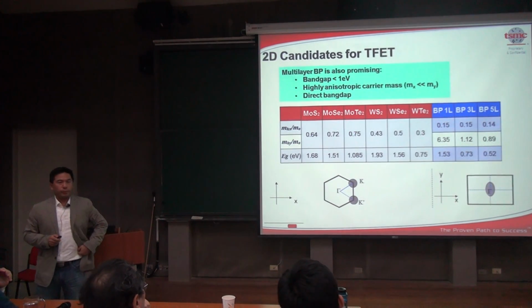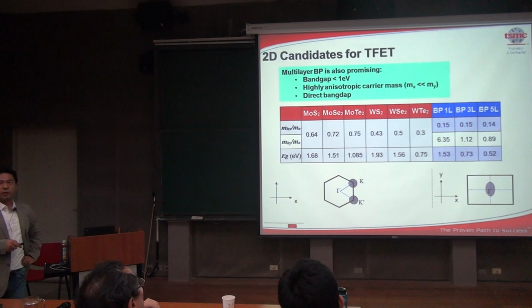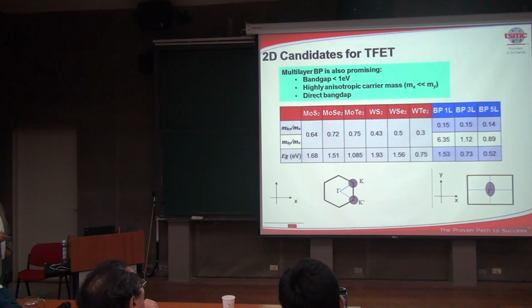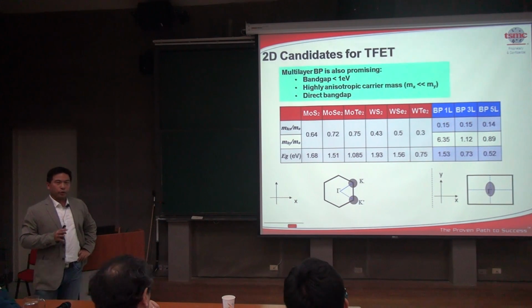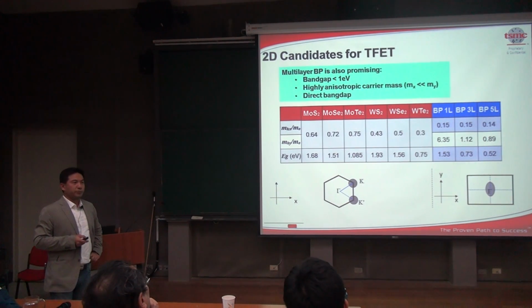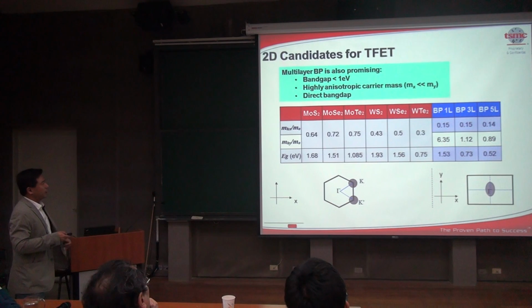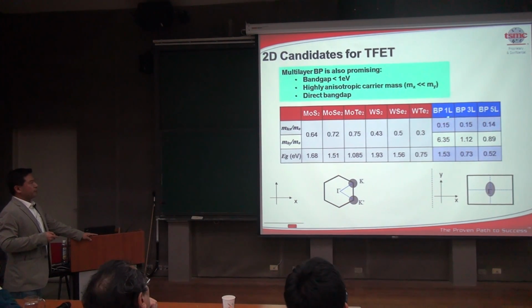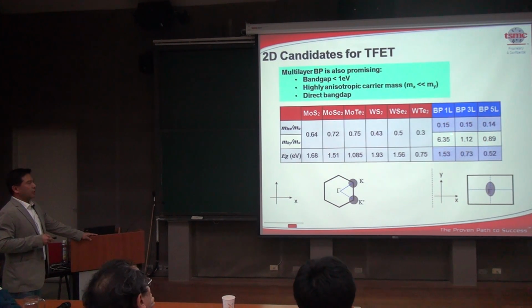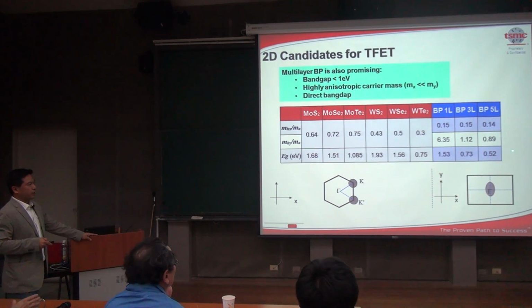And what about black phosphorus? There hasn't been much work done for black phosphorus yet, but from very simple band structure considerations, we can judge whether it could be superior to TMD materials. Now, black phosphorus has anisotropic carriers, so you have a very small effective mass in one direction and a larger effective mass in the other direction. That actually gives you an advantage of small effective mass. And the band gap could become as small as half a volt. So this is also an advantage.